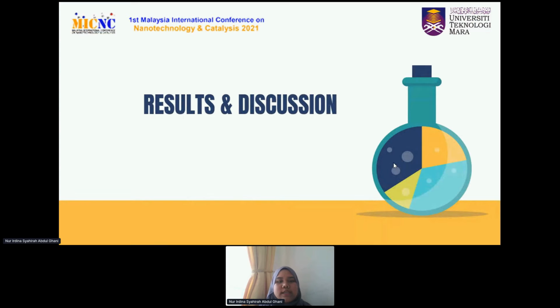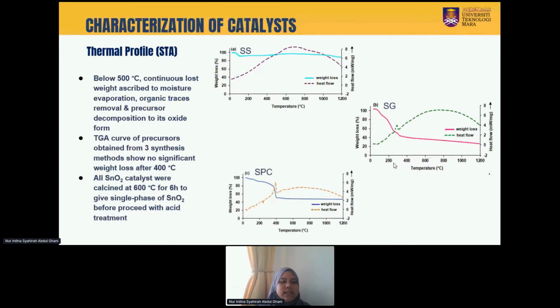For the results and discussion, for the characterization of the catalyst from STA, we can see from these three graphs: this is the precursor of tin oxide from solid state, sol gel, and also SPC. Below 500 degrees Celsius, the loss rate is ascribed to moisture evaporation, organic traces removal, and precursor decomposition to its oxide form.